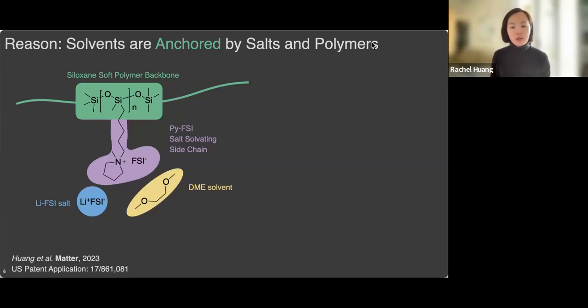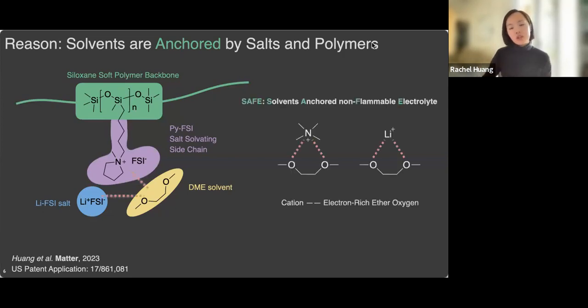And then we added DME solvent molecules. In this system, the electron-rich oxygen in the DME molecules likes to coordinate and interact with the positively charged nitrogen and lithium groups. Those interactions, or coordinations, effectively anchor those solvent molecules in the system, making them no longer volatile. Those anchoring interactions were confirmed with DFT and Raman spectroscopy. We call this special type of electrolyte SAFE, solvent-anchored, non-flammable electrolytes.